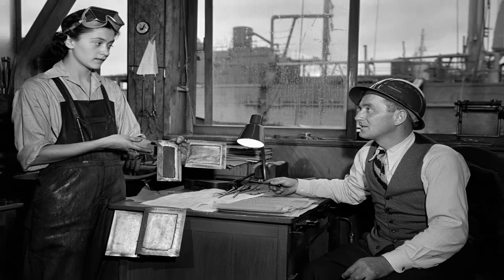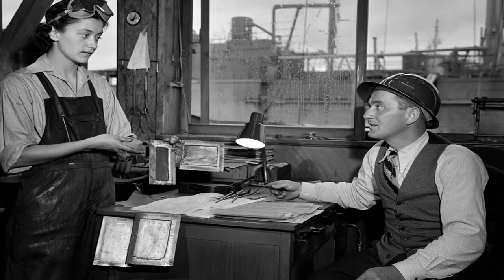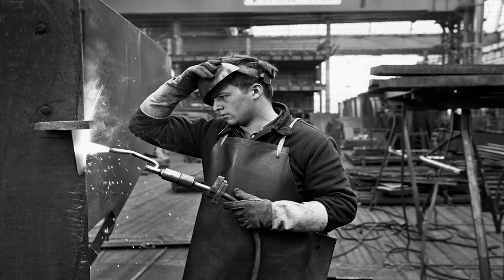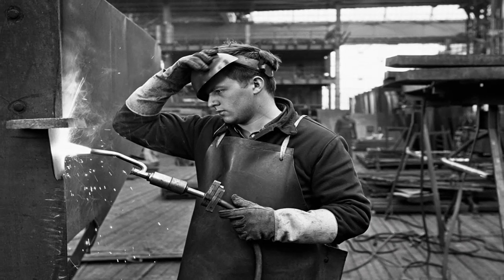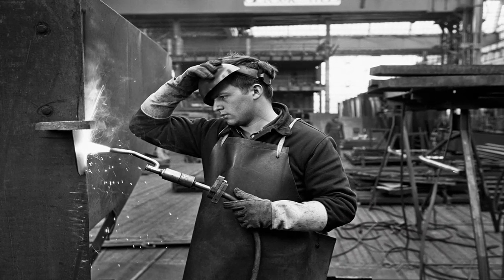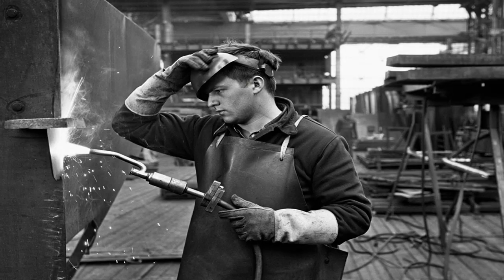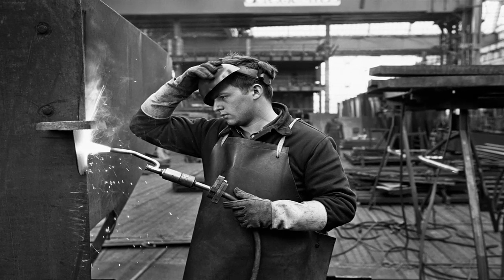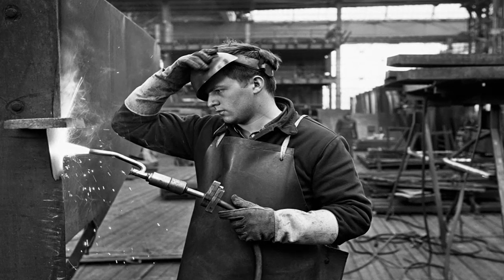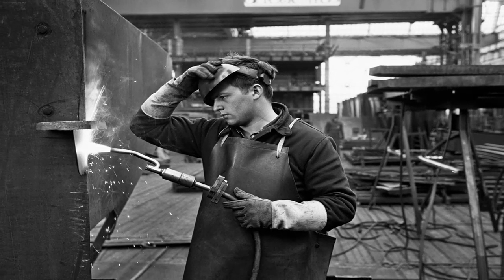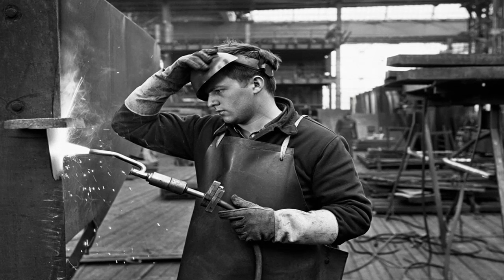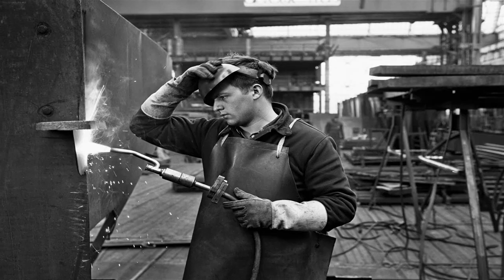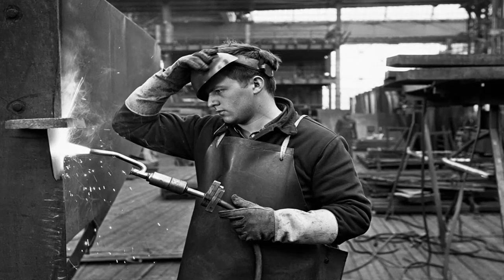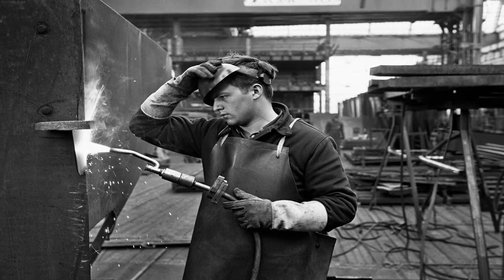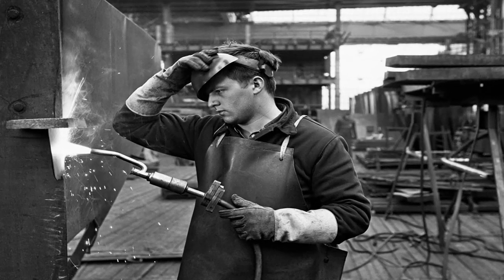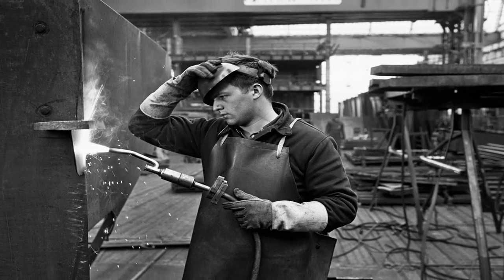One decided to monitor the assembly line on Hamill's overnight rotation. His first-hand view validated her findings. The welders were, in effect, inflicting damage on the metal, imposing strains that the plates would endure throughout their operational lifespan. Each successive weld introduced lingering pressures as it cooled. The building order caused these tensions to build up and focus at particular spots, especially around hatch corners and other vulnerable areas prone to stress buildup. Upon encountering the icy waters of the North Atlantic, the plates turned fragile. This trapped internal strain, coupled with the material's brittleness, set the stage for sudden, devastating breaks.